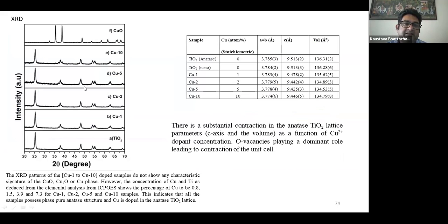If we check the XRD parameters, we find that we are doping copper in the titanium system. Copper is in either +1 or +2 state, and titanium is in +4 state. What we envisage is that the Cu-O bond will be longer than the Ti4+-O bond, so if we dope copper, we would think that the lattice will increase. However, what we found is that the lattice volume decreased. That can only happen if there is some vacancy. So overall, there is a definite amount of oxygen vacancy being produced in the system.